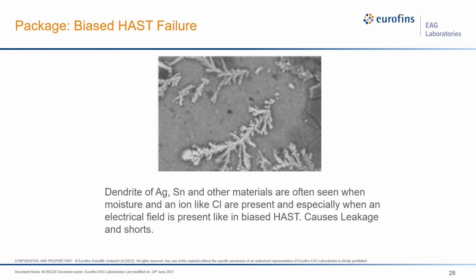Here we're looking at a failure mechanism following biased HAST. During the electrical testing, one of the more typical failures that occur following HAST is higher leakage. The biased HAST environment of the electrical biasing, the temperature and humidity creates an electrochemical reaction that promotes dendrite growth. This dendrite growth occurs in materials such as silver, copper, or tin within the package. This dendrite growth will create a leakage between different circuits of the package and cause it to fail the electrical testing.